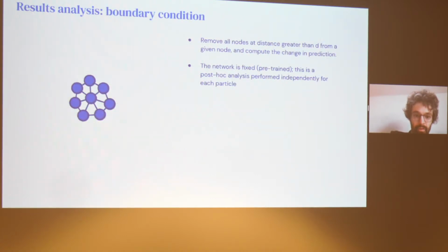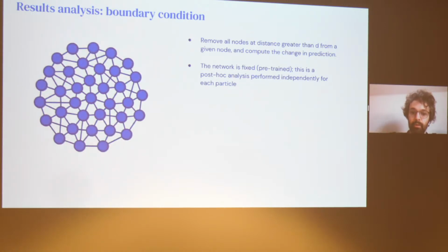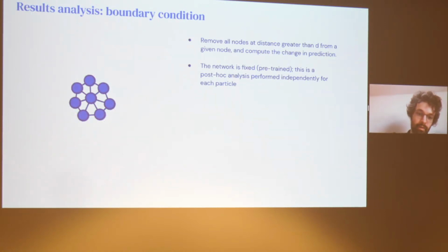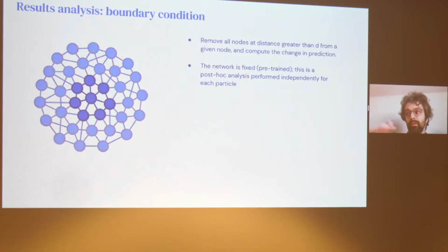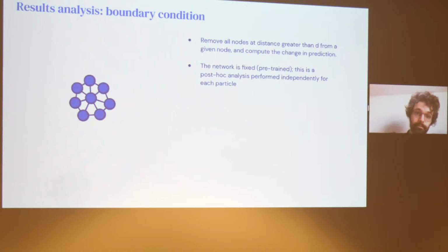So the first thing we did is change the boundary condition. When you make the prediction for a given node, you typically see the neighborhood at a large distance. This is because the network is applied, I think in this case, 5 times, so that means you see at distance 5 for a given particle. But now you can pretend that the neighborhood at a given distance is not there. So you change the boundary condition, you reduce it, and you look at whether the prediction changes. If the network is extremely local, if it only looked at the neighbors of a given particle, then that wouldn't change things as long as you keep the immediate neighbors. But if the network is using information from very far away, then that will modify the prediction.